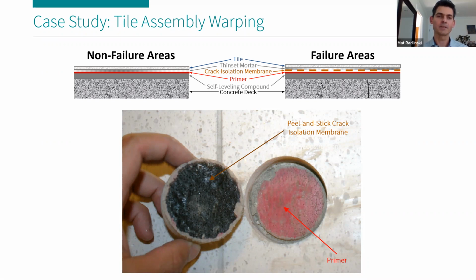And the failure mechanism is really kind of a perfect storm of three different things happening. We had a thin-set mortar that, for whatever reason, required a fairly high amount of water to be added during mixing. That water from mixing was apparently capable of saturating fairly high absorption tile installed on top of it, which allowed for warpage of the tile. And because the underlying crack isolation membrane underneath the thin-set mortar was a peel and stick product that didn't have, as you could probably guess, a very strong adhesion to the substrate, that allowed for debonding of the membrane along the edges.